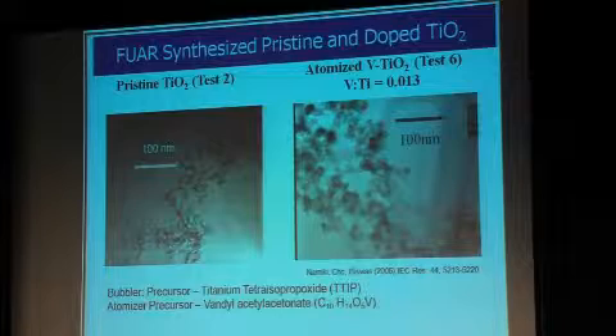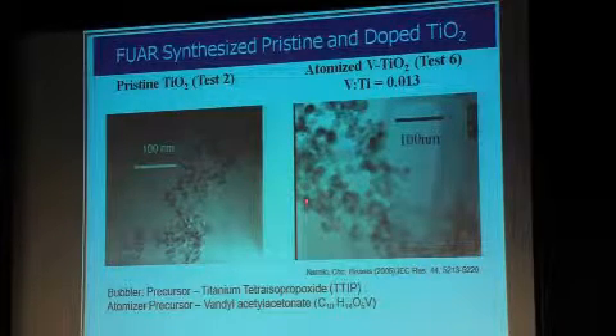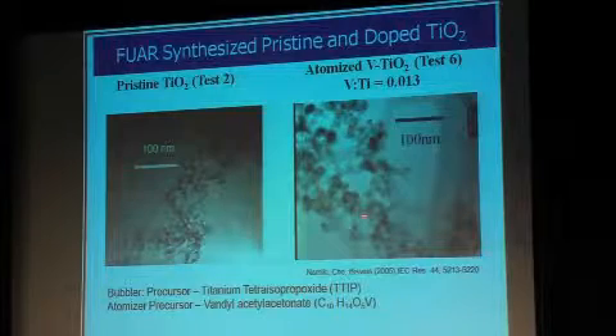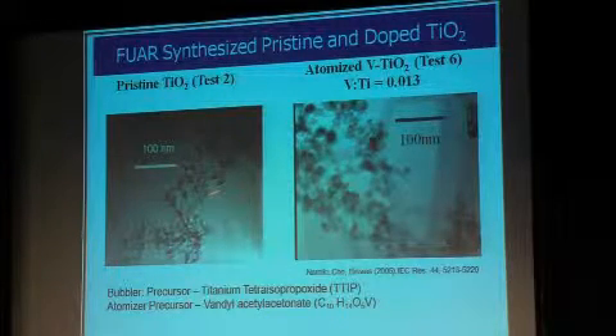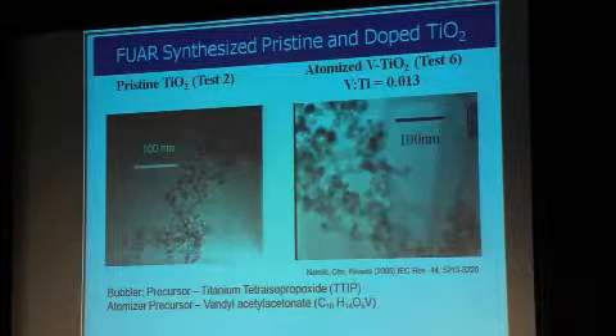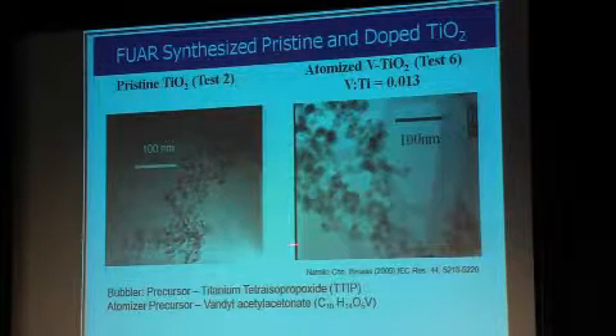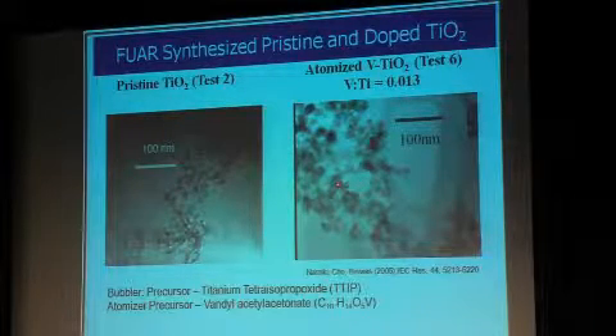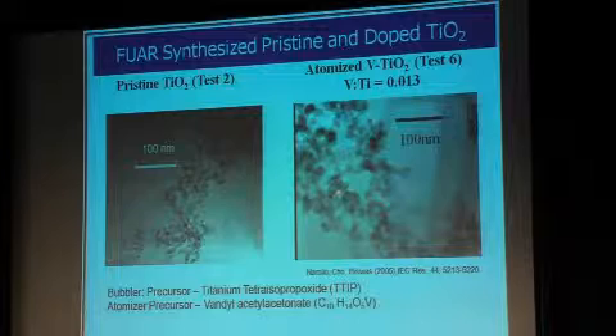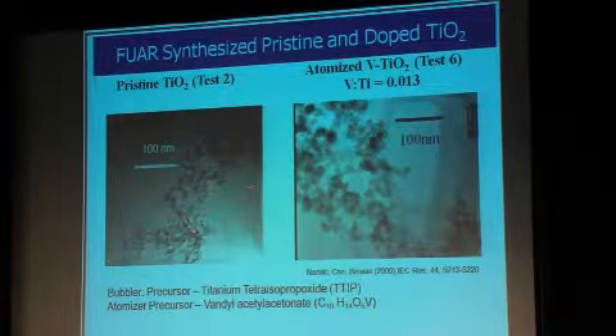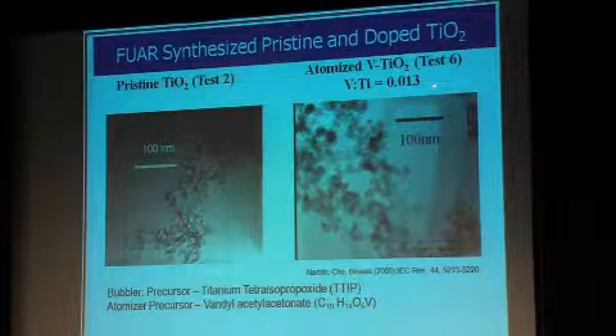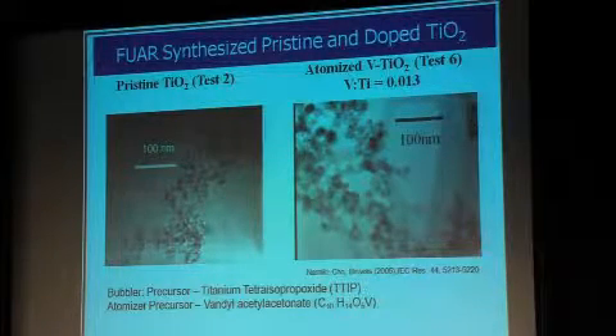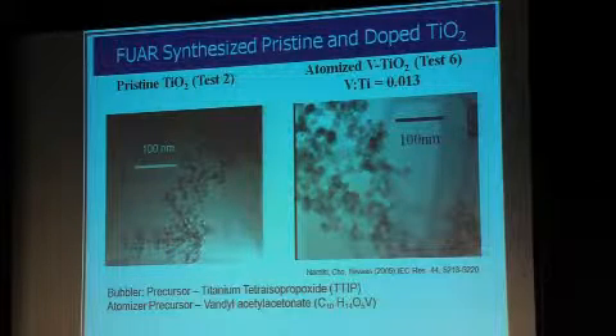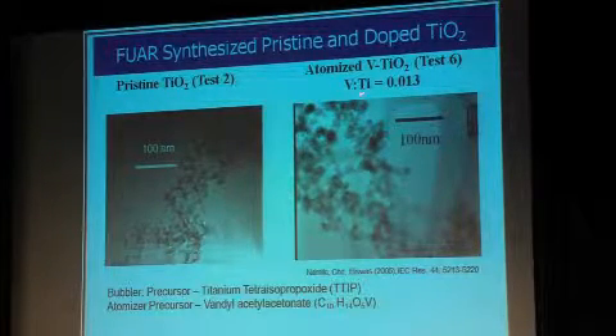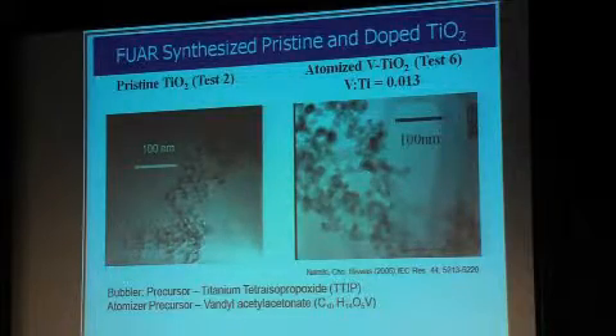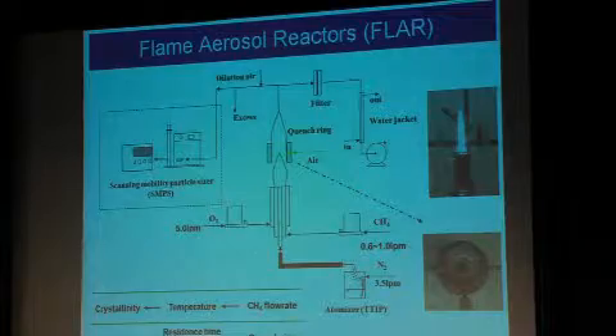I add a small amount of vanadium, and you can clearly see that, of course, the structure looks similar, but the primary particle that I talked about is much greater in this case compared to this. A small amount of vanadium changes the entire particle dynamics towards the downstream side and promotes sintering, and as a result gets me a much larger primary particle. And of course we can tune these. If I want to match it, I can add a very small amount of titanium or vanadium, or reduce the residence time and get the desired materials. But one has to be very careful. If I wanted to just study the effect of vanadium on this, but you can see the primary particle size itself has changed.